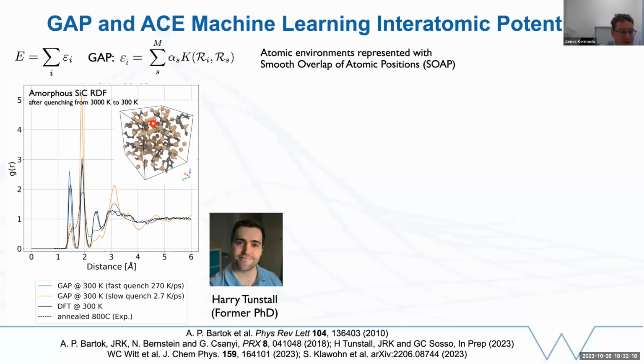And the advantage of having an interatomic potential like a GAP is that you can then go and use a bigger system and a longer timescale and do that quench more slowly. And when we do that, we get the orange result, where for the first peak of the radial distribution function, at least, we're starting to get better agreement with experiment. But there's still a bit to understand here. And our current hypothesis is that this experiment isn't showing a single structure. It's averaged over a few different structures. And that's why we're not yet getting comprehensive agreement with that.